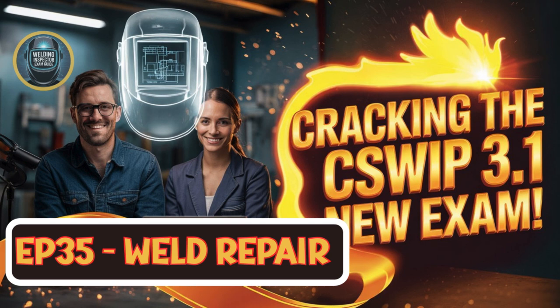And PWHT comes back into play here too. It can, yes. For preventing stress corrosion cracking, for example, PWHT may be necessary specifically to restore the correct metallurgical microstructure, reduce that dangerous hardness, and alleviate the residual stress that drives the cracking.